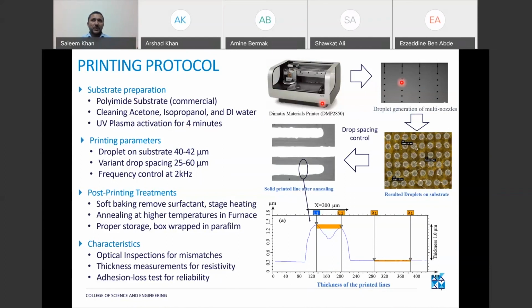First, we tune the material so that we achieve uniform, synchronous droplets. As you can see here, this is a picture taken from the system. Here we have a very synchronous deposition of these droplets. We can control the speed and the frequency of the droplets, and the final resolution on the substrates is dependent on the frequency and the speed of the droplets. We tune these parameters and keep the droplet spacing such that we achieve very uniform layers. Here we first do deposition on the substrate, we record the droplet size, and then we adjust the droplet spacing so that we achieve this type of lines or patterns on the target substrates.